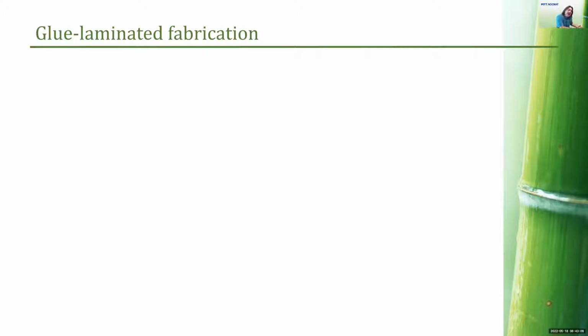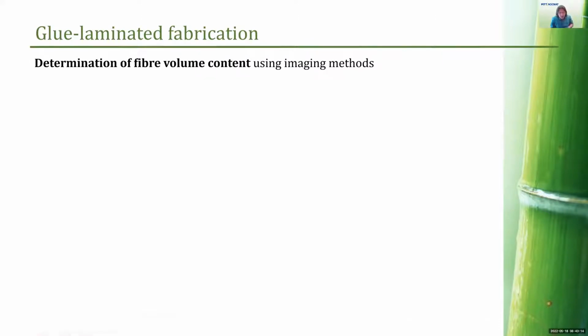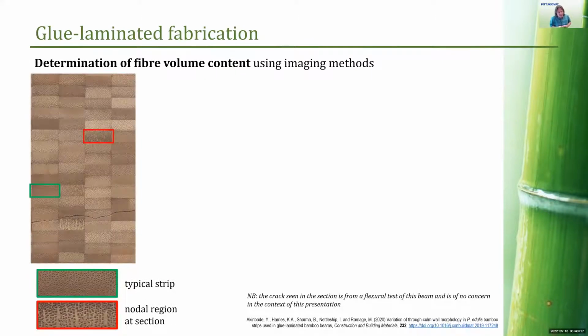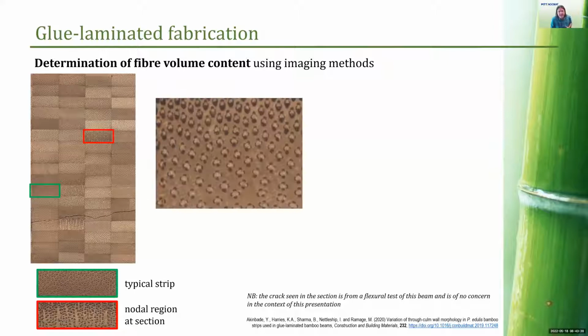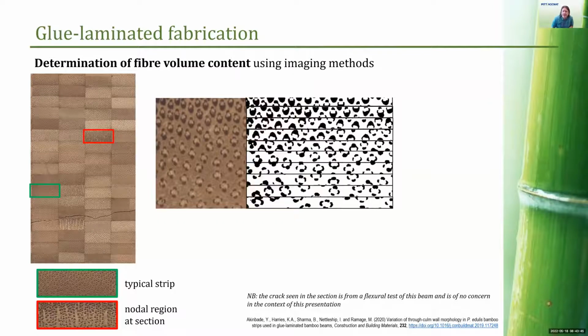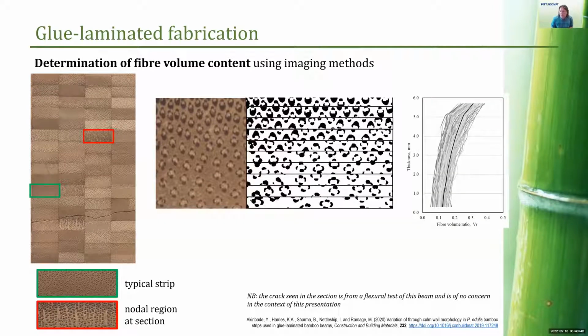I now want to skip to after we have fabricated our laminated materials. And we did a study a couple of years ago that looked at a large number of beams. This is just a photograph of a cross section of one of them. These beams have been tested in flexure, and so that's why you see that crack in them. That's not important to what we're doing, but we're looking at quantifying actually the fiber volume ratios and the consistency of the strips themselves. And we did that using optical methods. And so we isolated each of the strip elements, we digitized it, and determined the fiber volume ratio.